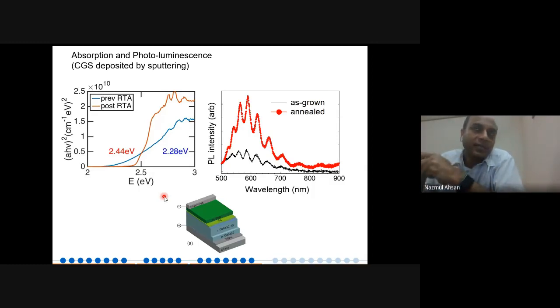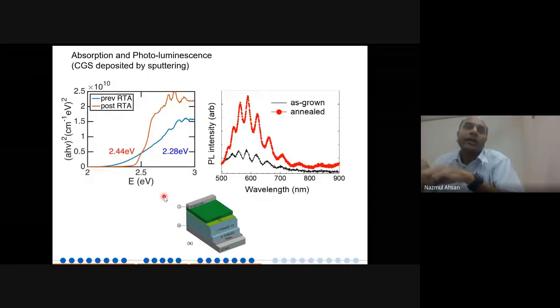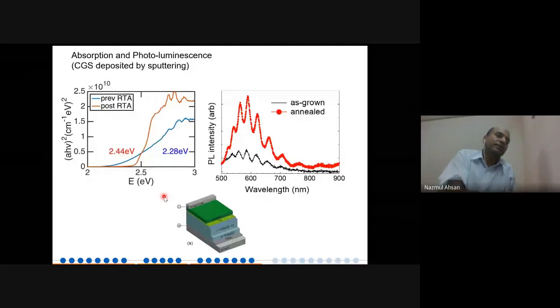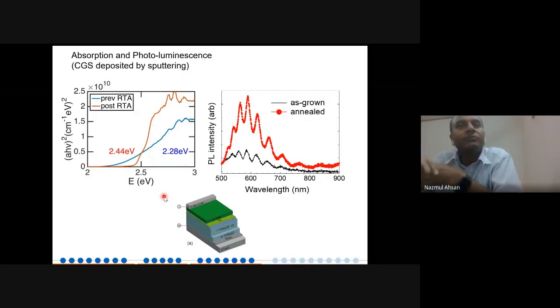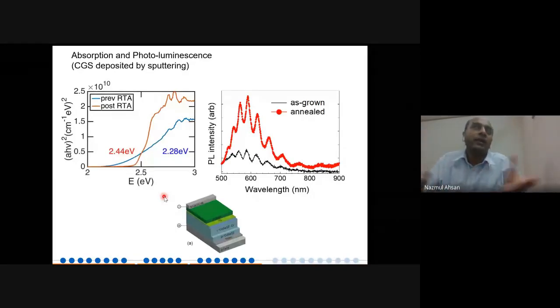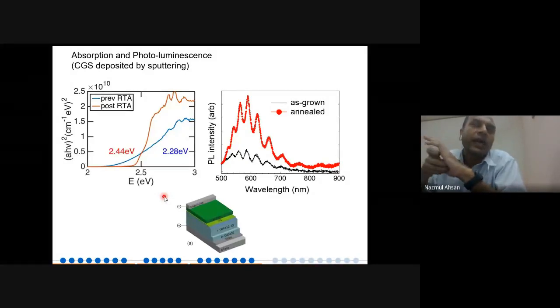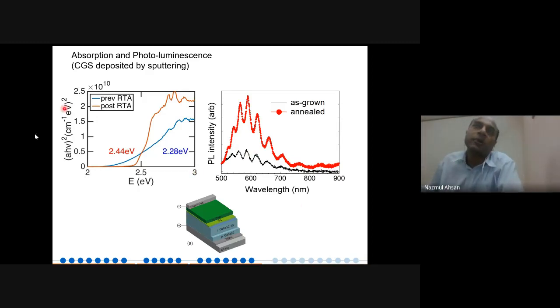Most of the CGS technology today is you make the thin film, and then bring the sample outside the chamber and do sulfurization. If you do that, the good thing is you have more freedom. But the bad thing is, once you expose your high quality material to the air, you have to compromise the interface quality. And in a solar cell, it is very important that you don't put defects in your interface and make your interface high quality. To do that, if you can somehow make all your process inside a vacuum environment, that gives you fewer defects. And that's why we are optimizing our sputtering system.